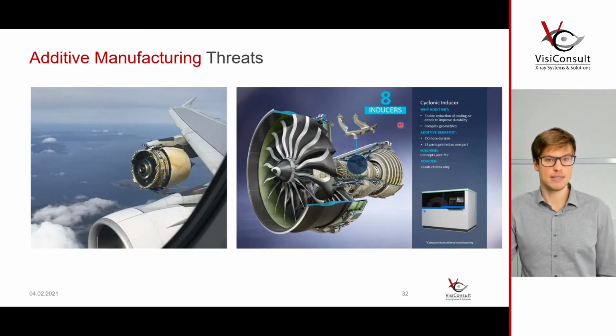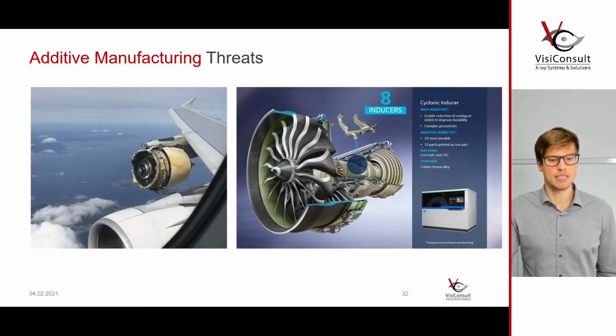Because there are companies that are starting to bring these additively manufactured components in safety critical environments like turbines. And the image here on the left, this is no additive manufacturing failure, so bear with me, as there are so little flying parts, so I don't have a picture showing an actual additive manufacturing failure. But even with traditional NDT methods, you see failures on parts. Like here, it was a fan disk failure because a crack did not get noticed. So it led to an uncontained engine failure. Pretty critical. But as we are now bringing additive manufacturing into these turbines and critical environments, we have to be absolutely sure that what we do can be inspected and can be inspected well.